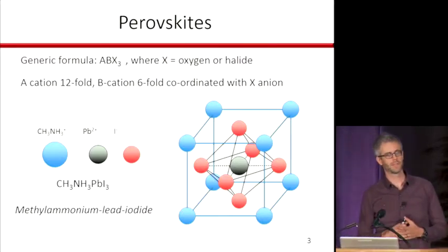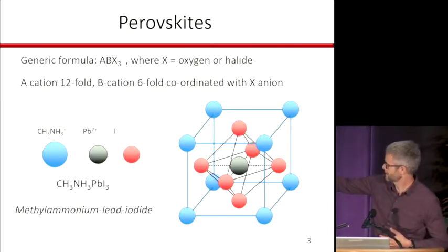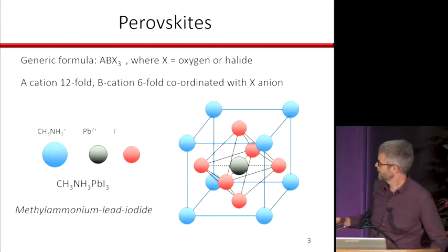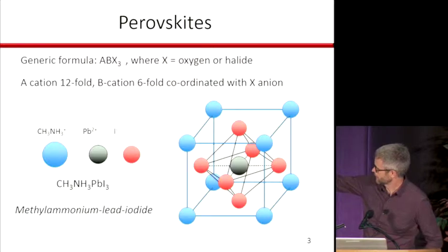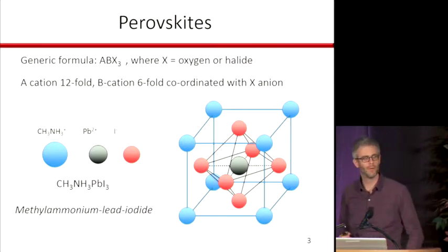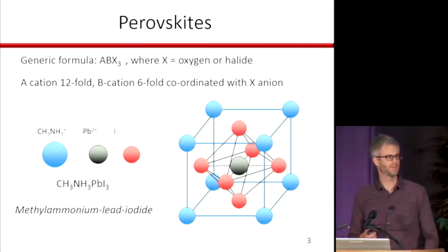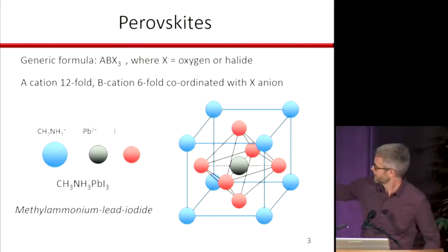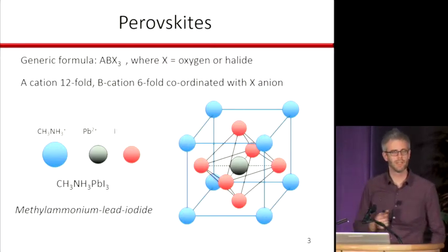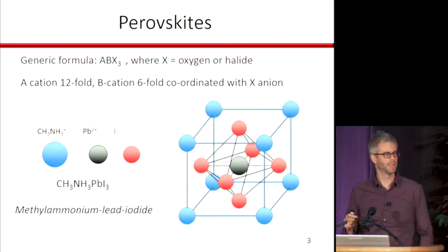This slide shows you the crystal structure of the unit cell of the perovskite, and it usually has lead in the center, but sometimes people put tin in there. Here there's an octahedral cage of iodine around it, but you can replace that with bromine or even chlorine to increase the band gap, which turns out to be important for solar applications. There's an organic cation out here, methylammonium, and you can change the size of that and put in other components and fine-tune the band gap.